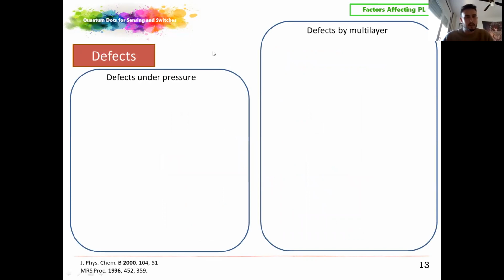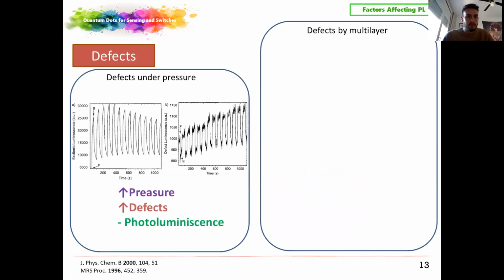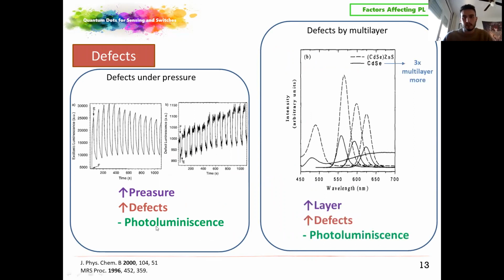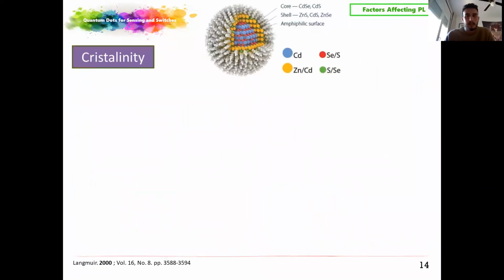This is a very good property. Also, defects are important to control because defects in the nanocrystal can promote a decrease of the photoluminescence. Also, the multi-layers can promote an increase of the defects, decreasing the photoluminescence of the nanocrystals, resulting in a lower quantum yield.